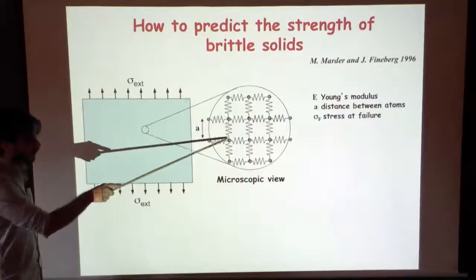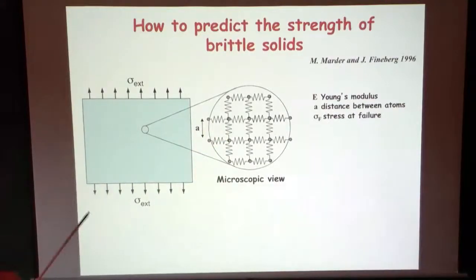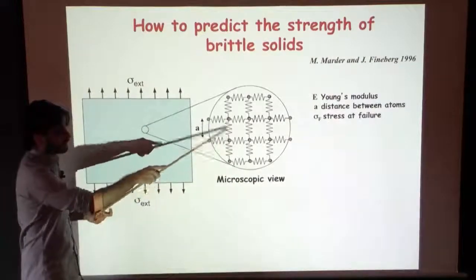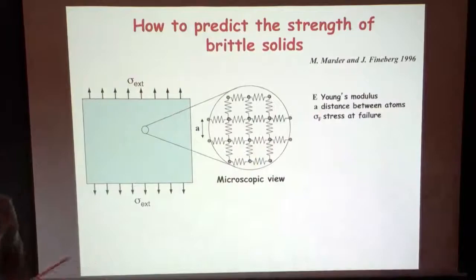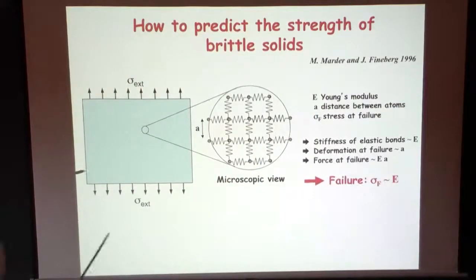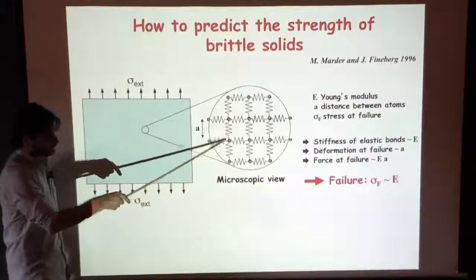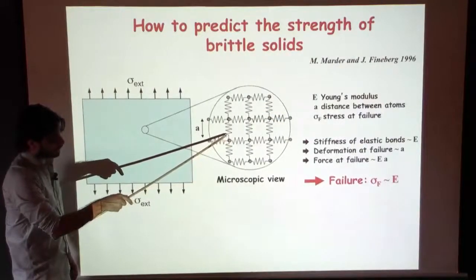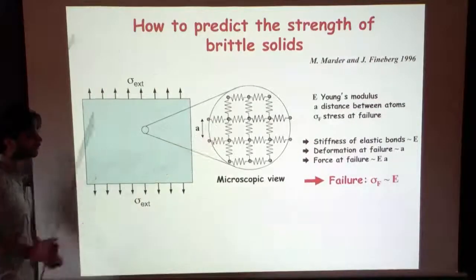Then you just take a failure criterion based on deformation of the springs and say that your material will break when springs are deformed over a length that is a typical distance between atoms, the interatomic distance. And so then you get the stiffness of your spring from the elastic modulus of your material, from the Young modulus, and you get a failure stress that is typically of the order of the Young modulus. Maybe the Young modulus over 5 if you make a more elaborate calculation on when two atoms get separated from each other and don't interact anymore.